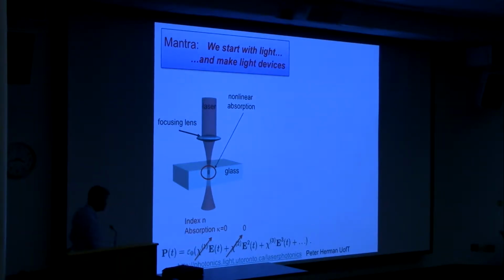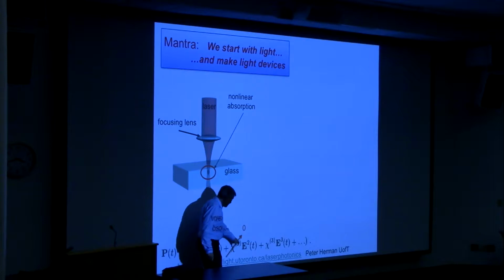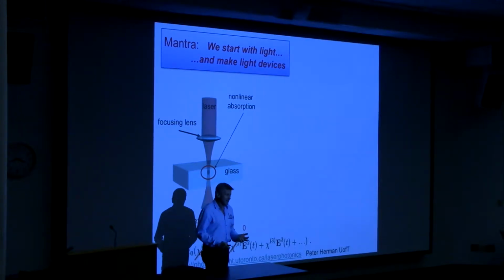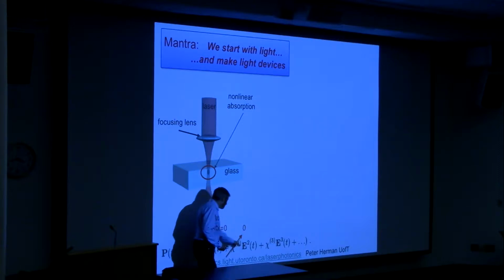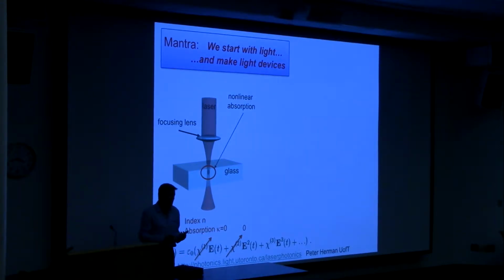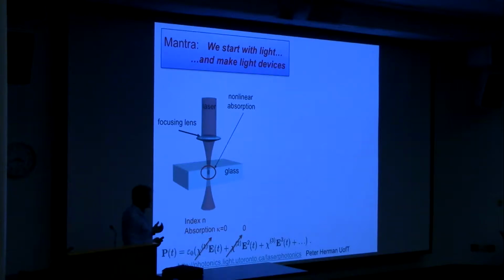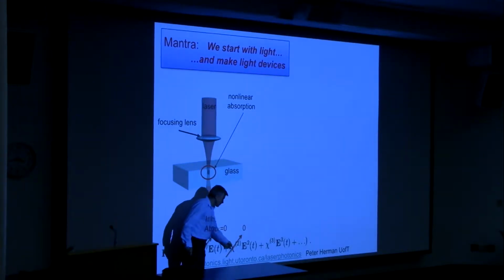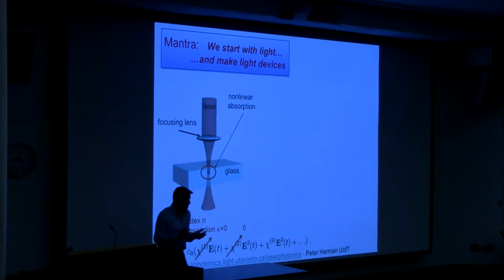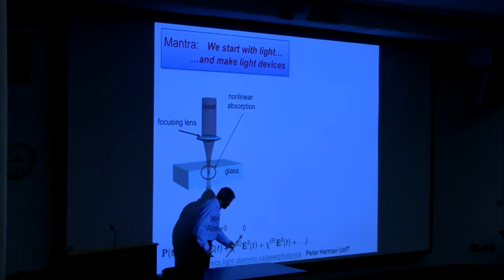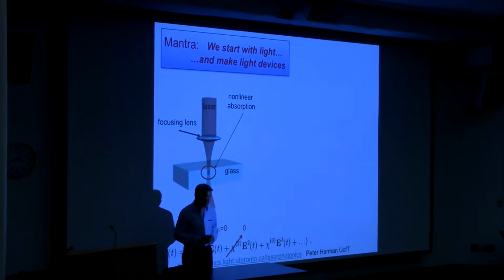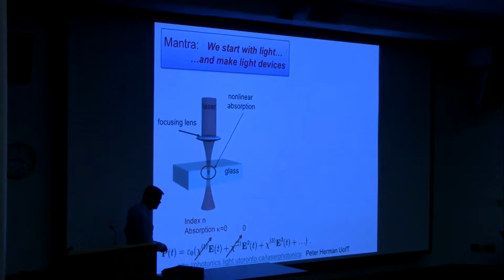We have to go to higher order terms. All right, so if we look at chi 2, it's not that hard to prove that if we reverse the direction of the electric field, you get a conflict mathematically, which means that there's symmetry inversion in the material, and you cannot make second order interactions with the material. We have things called doubling crystals. They don't have inversion symmetry, but glass does have inversion symmetry. It just turns out it's hopeless that you can drive second harmonic effects inside the bulk of glass. So that's a well-known effect from nonlinear optics.